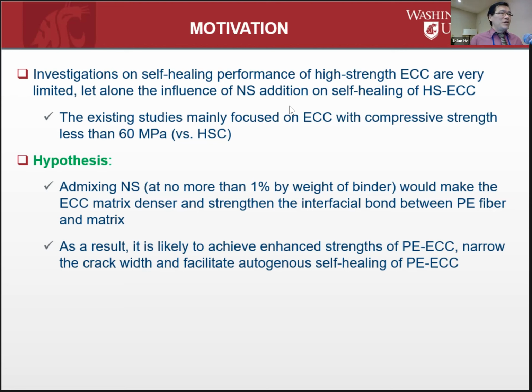We'll talk about this a little bit, just like the SMA, where we were talking about the bonding earlier. Sometimes it's a tricky balancing act, how strong you want to make the matrix versus the bond. We'll get into that. But the hypothesis is that the nanosilica will do the magic and help us achieve that balancing act. The other hypothesis is that with the nanosilica, we'll be able to close the gap. Instead of 150 microns, we can make the crack width much narrower so that it will facilitate the autogenous self-healing.